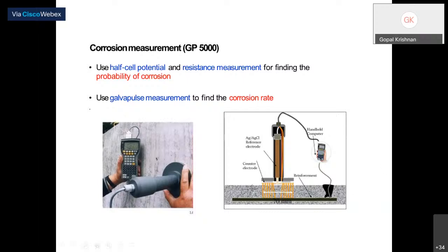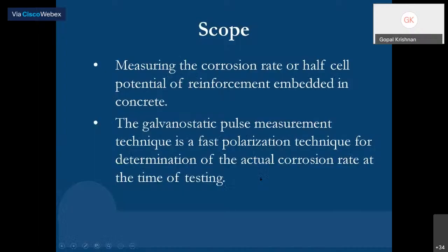The important thing here is that we are using a silver chloride electrode. Generally, when you see half-cell potential readings, they use copper sulfate, but silver chloride is much more accurate. The scope is measuring the corrosion rate, half-cell potential, and resistivity, as I said.